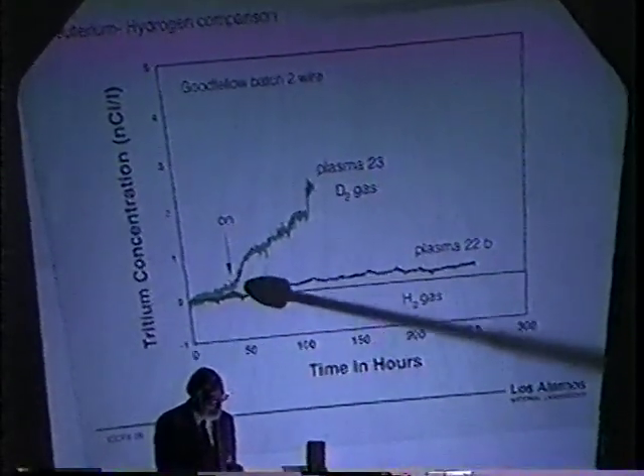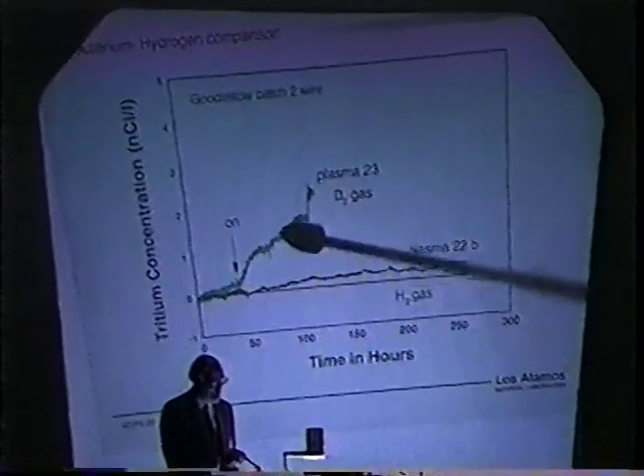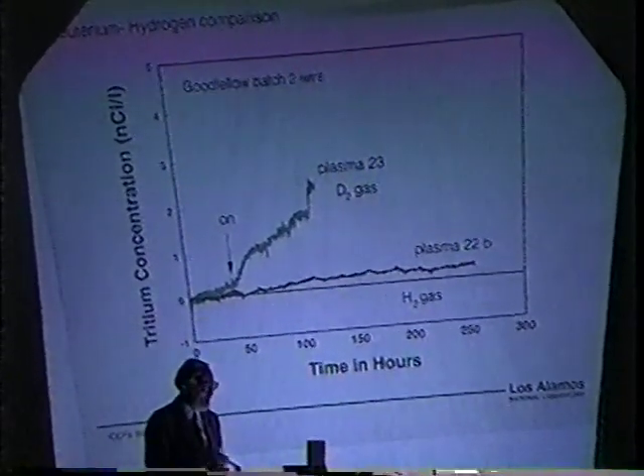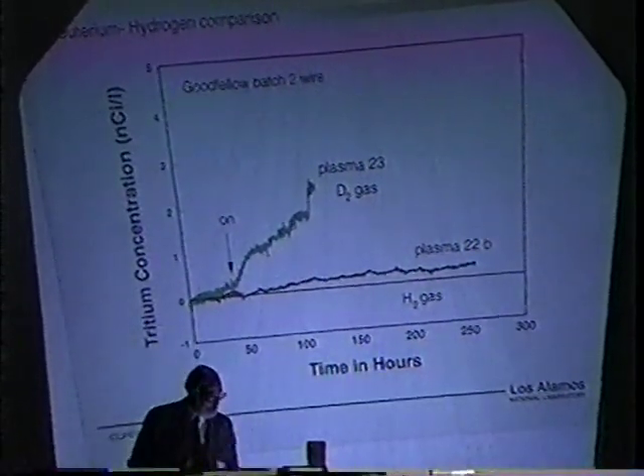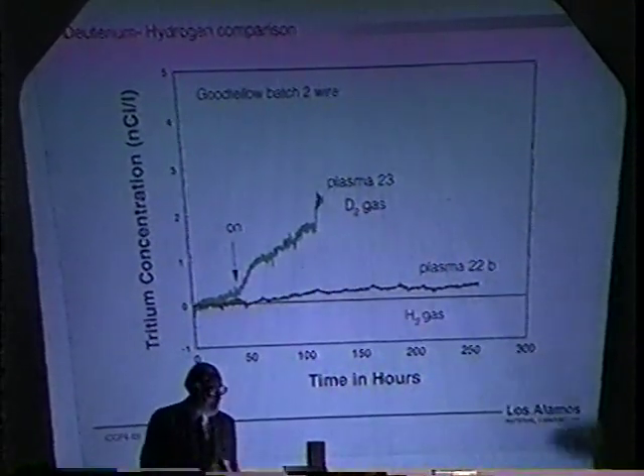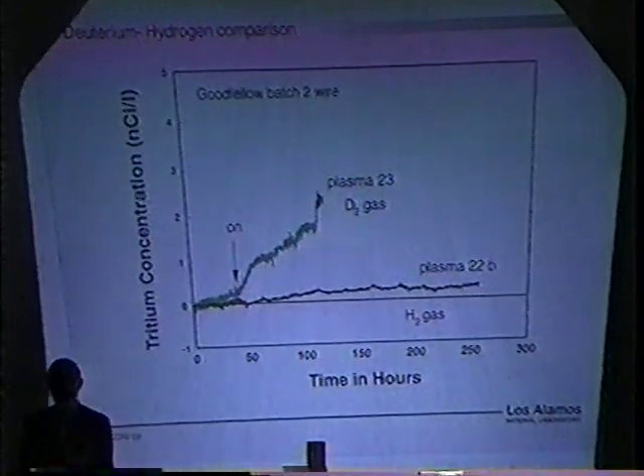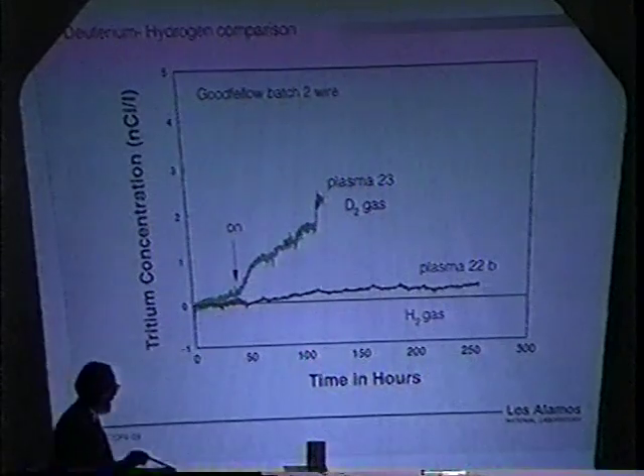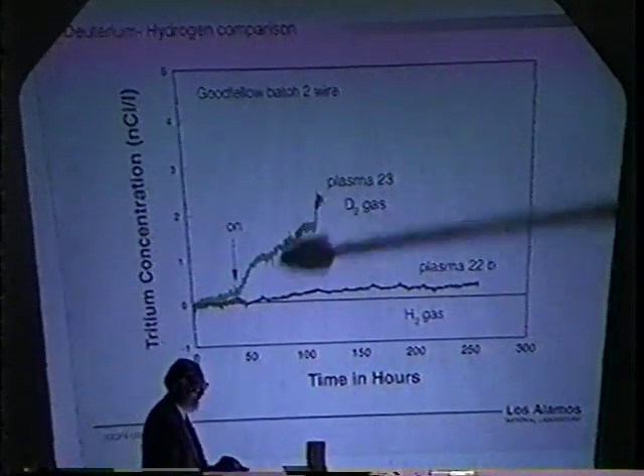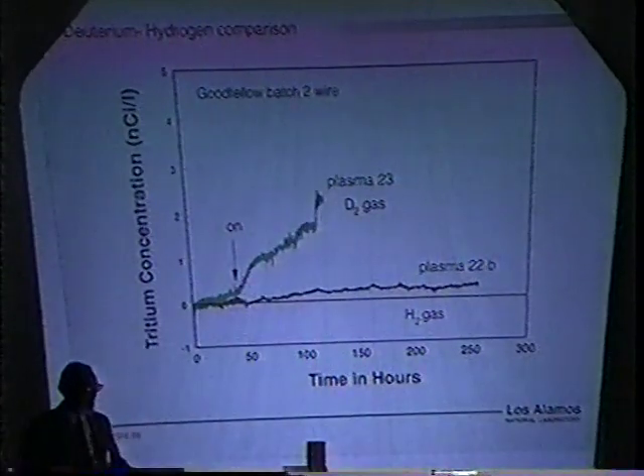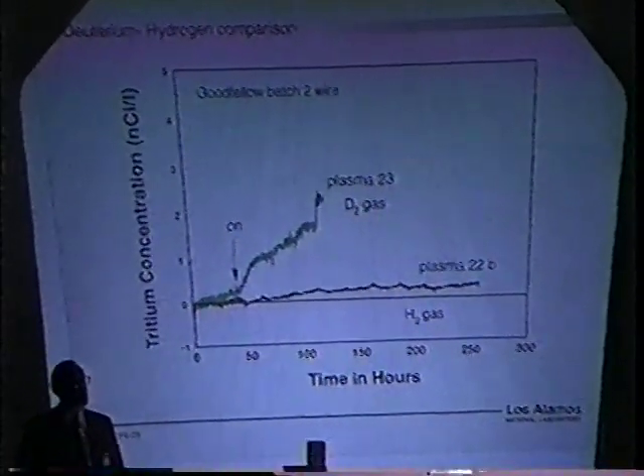Here's another example. Deuterium gas, plasma's on, the tritium begins to rise. This is the tritium concentration in nanocuries per liter. This is the Goodfellow wire that I was telling you was so good. You can see that it really is quite spectacular. There's no ambiguity about it at all. And the tritium then is oxidized out as water, subjected to scintillation counting, so you know absolutely that it's tritium. There's no room for skepticism, at least in these measurements.